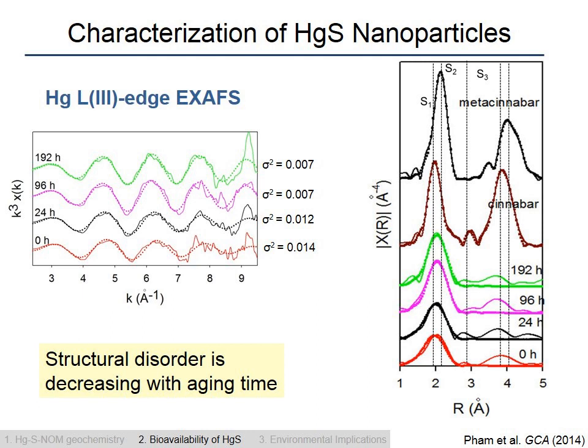So the graph on the left is showing the absorption signal as a function of the X-ray energy or wave number. And these oscillations are due to the absorbed radiation interacting with the atoms that neighbor the mercury atoms in these mercury sulfide nanoparticles. You can take these oscillations, perform a Fourier transform, and you can get a radial distribution function of the mercury atoms and its surrounding atoms in the mercury sulfide structure.